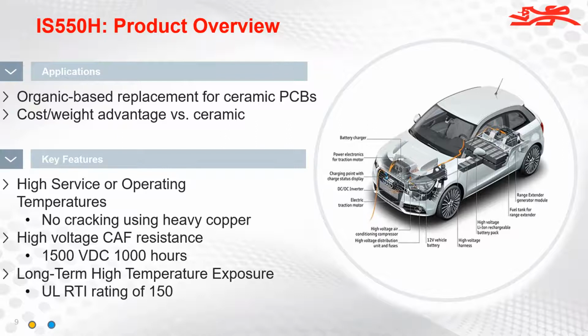Sorry about that. Okay. So obviously the high temperature operating conditions that these vehicles are going to see, either exposed to the environment near some of the battery packs or in some of the components that are in the vehicle, and so to be able to handle those temperatures, you need things like copper coins or various heavy copper features within the board that are going to draw that energy out of the board and pass that to the environment. And so when you install those embedded type of copper features into the board, you need something that while it's going through that copper cycling, that copper doesn't cause cracking or fracturing of the material, which is something that you would have to worry about using a polyimide or ceramic type of material. And so this is an area where this material excels and addresses that cracking issue.